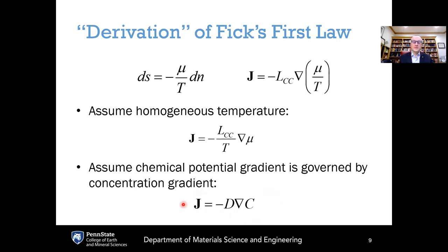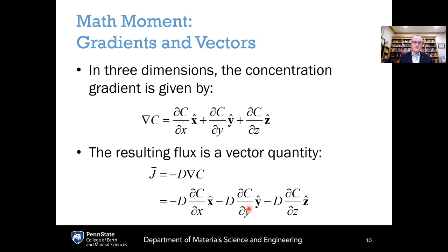And from that, we get this formulation here of Fick's first law, where it is the flux of matter equal to the minus sign here, because the flux acts to lessen the concentration profile, times D, our kinetic rate parameter, the diffusion coefficient, which governs how fast the kinetics occur, times our thermodynamic driving force, which is the gradient of the concentration. So this is Fick's first law and the steps that one needs to take to go backwards from Onsager's formulation of irreversible thermodynamics back to the phenomenological form of this flux equation proposed by Fick. Just a brief reminder here of the math involved.